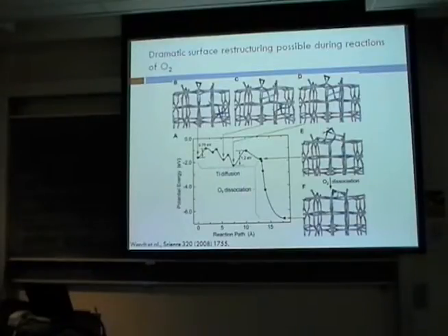So for example, in the dissociation of oxygen on titania, so this is an O2 negative that's adsorbed, using both STM and density functional theory, this group has seen that to do this dissociation, titanium actually migrates through interstitial spaces up in the bulk to the surface. And this extra titanium atom gets added to the surface, and then that's the titanium atom that promotes oxygen dissociation. So you can see some very complex mechanisms here.